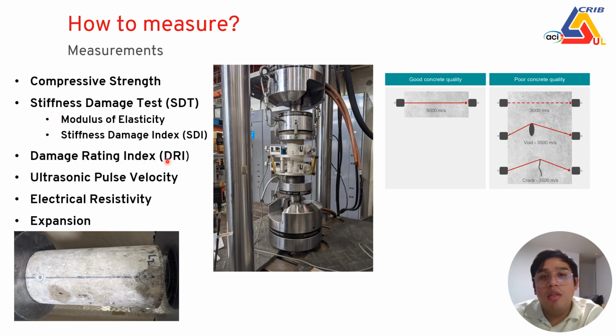The damage rating index, like in a concrete polished section, we try to quantify in squares of 1 centimeter by 1 centimeter the number of cracks in the cement paste or in the aggregate, with different products. We also use ultrasonic pulse velocity, electrical resistivity, and the expansion test to see which measurement can allow us to distinguish between a reactive and a non-reactive aggregate. So we do all this testing for a series of two aggregates that I'm going to present in the next slide.